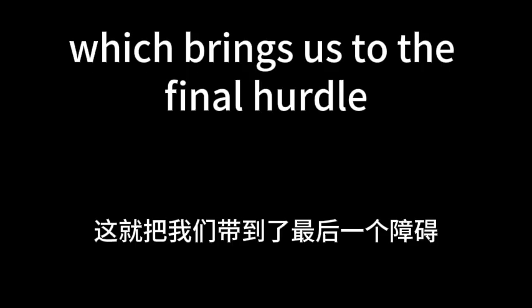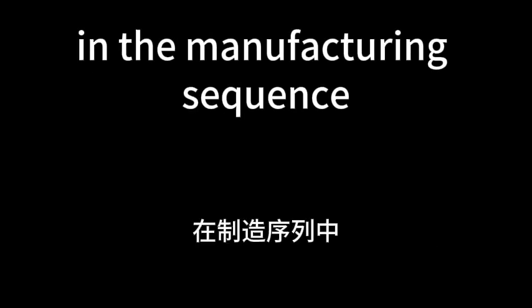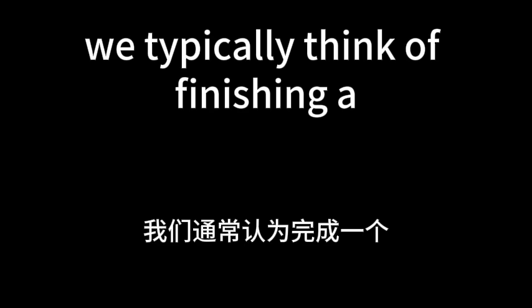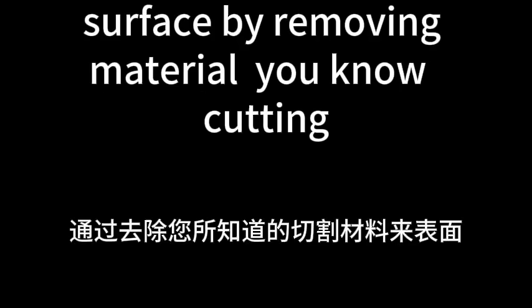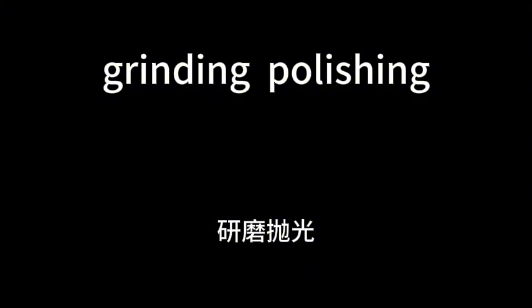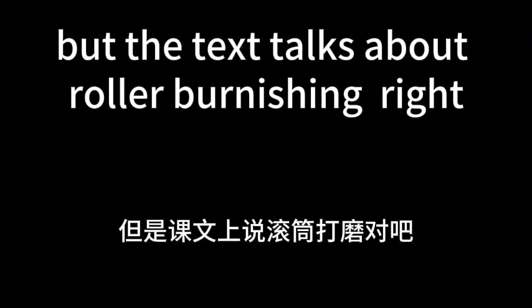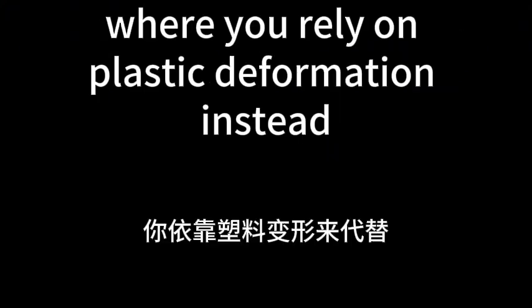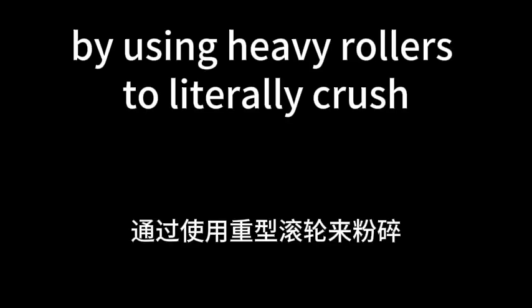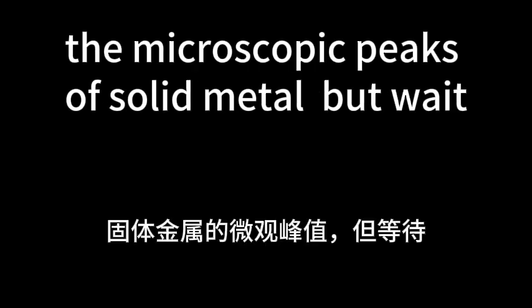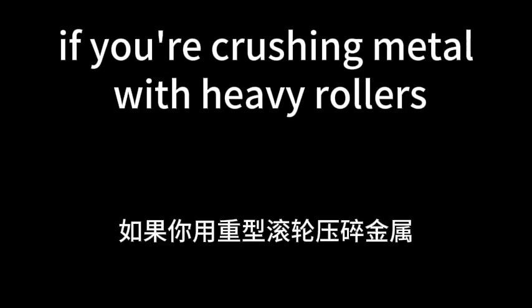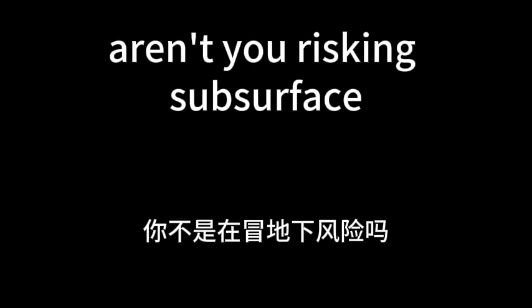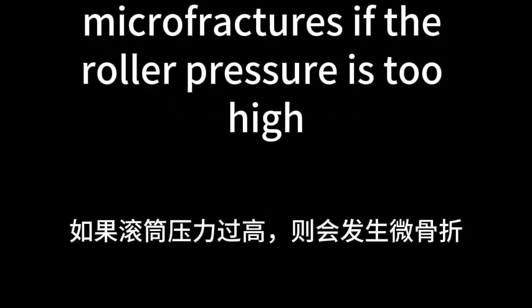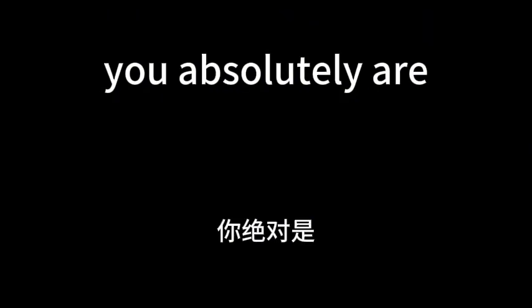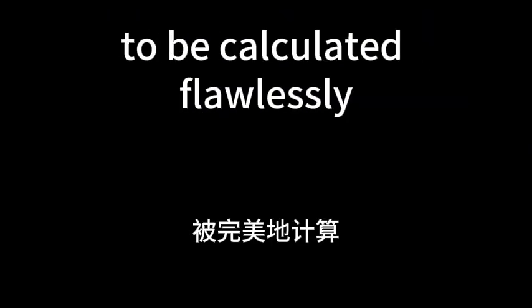Incredible. Which brings us to the final hurdle in the manufacturing sequence. We typically think of finishing a surface by removing material: cutting, grinding, polishing. But the deck talks about roller burnishing. Right, where you're relying on plastic deformation instead, by using heavy rollers to literally crush the microscopic peaks of solid metal. But wait, if you're crushing metal with heavy rollers, aren't you risking subsurface microfractures if the roller pressure is too high? You absolutely are, which is why the pressure load has to be calculated flawlessly.